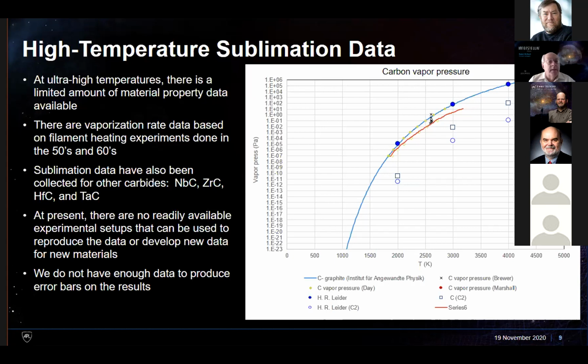Again, one of the big issues is how you measure temperatures at these temperatures. One of the big things you're doing when measuring temperature is saying, I know what the vaporization rate is, so if I can measure the vaporization rate, I know what the temperature is, but that implies you know what the temperature is too. So again, we don't have a good way to put error bars on these numbers. There's not a lot of data out there, and uncertainty drives the margin, and as you put margin here, the whole design gets bigger and heavier.